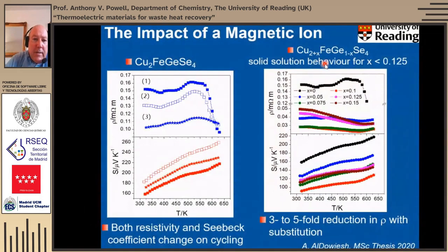and hopefully improve the transport properties. There's one slight fly in the ointment with this phase, and we still don't fully understand this yet. If we do the measurements of the resistivity and the Seebeck on cycling, we find that actually the resistivity gradually falls from the first to the second to the third cycle. After the third cycle, it's more or less a constant value, and we see corresponding changes in the Seebeck as well. We're not quite sure why that is yet, because any thermal analysis that we've done suggests that the changes occur at significantly higher temperatures than we're getting to here.